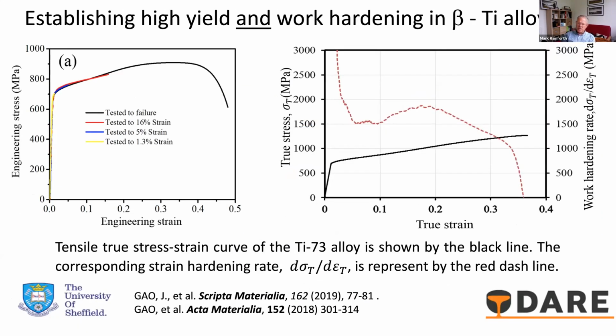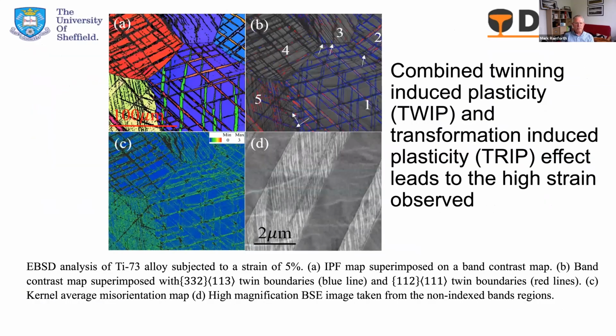But again, it's a very similar story to the steel. The parallels are very similar in terms of developing an alloy that can offer you both high yield strength and high work hardening, so that we get the good mechanical properties, but equally that has additions that are quite straightforward, like iron, chromium, and so on. So this is one alloy where we have achieved that. We've got a yield strength of 700 megapascals, which is high for a beta titanium alloy, and also nice uniform work hardening that takes us to a true strain of 0.4, which again is very substantial. And as I say, the parallels with the steel is very similar.